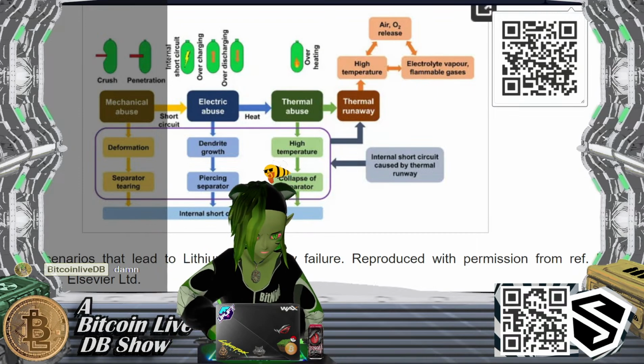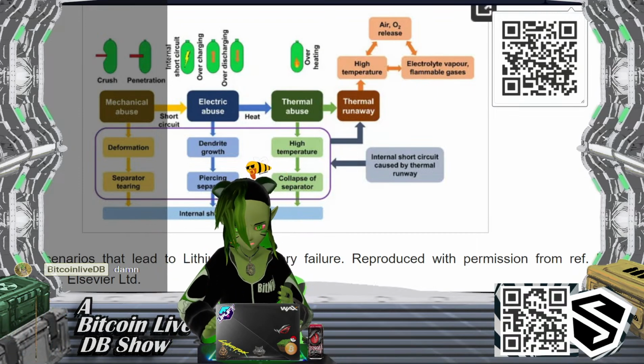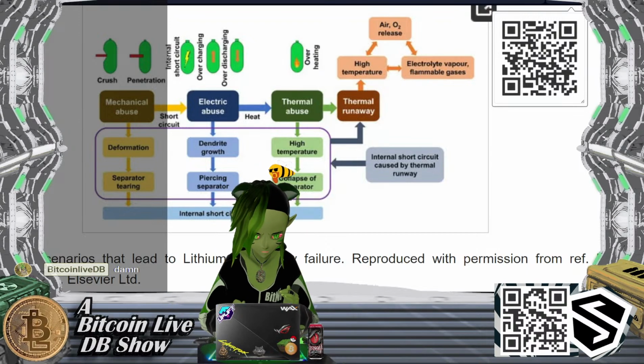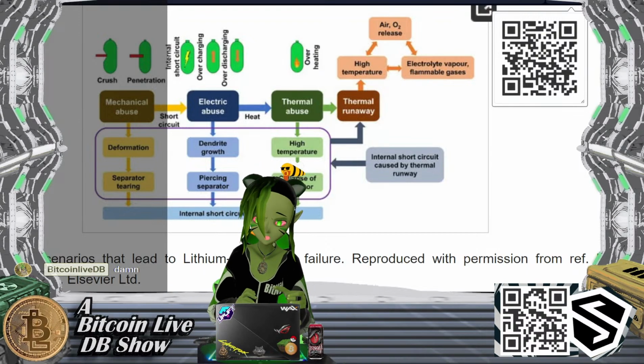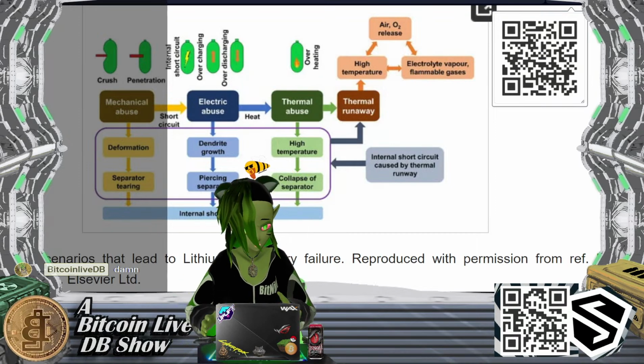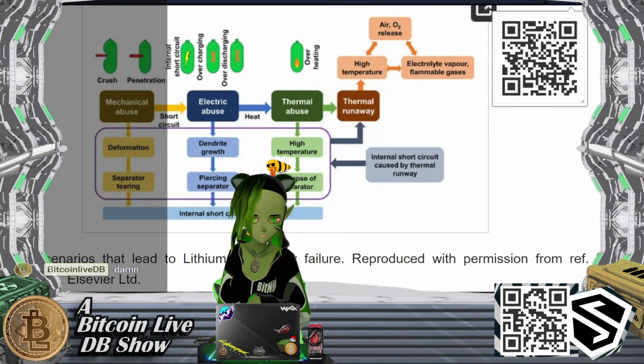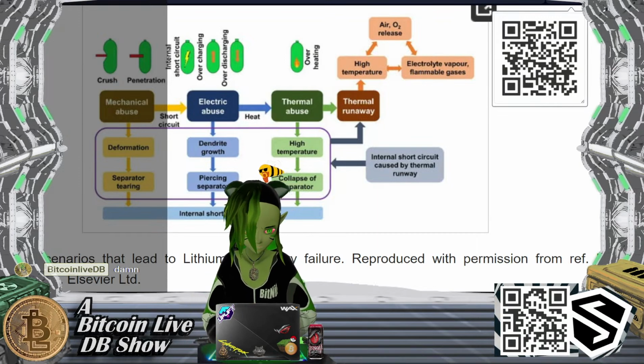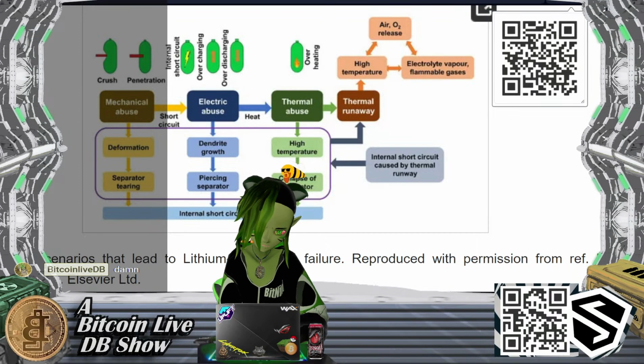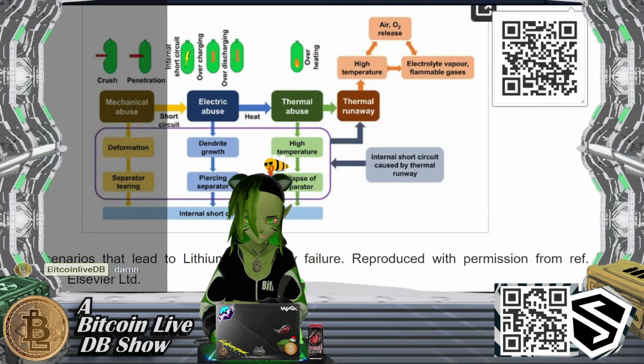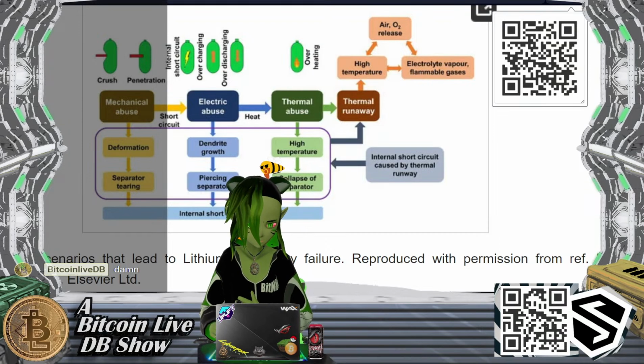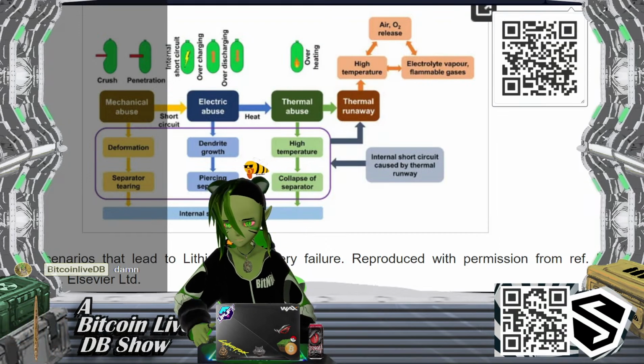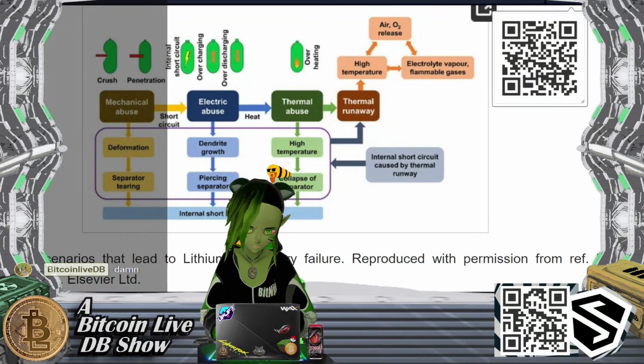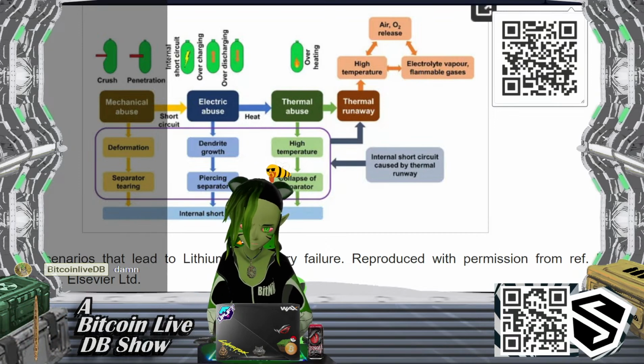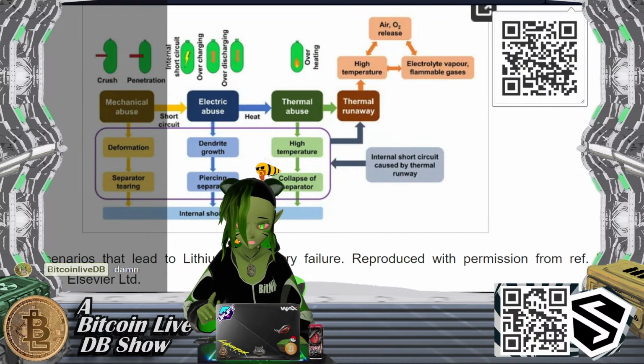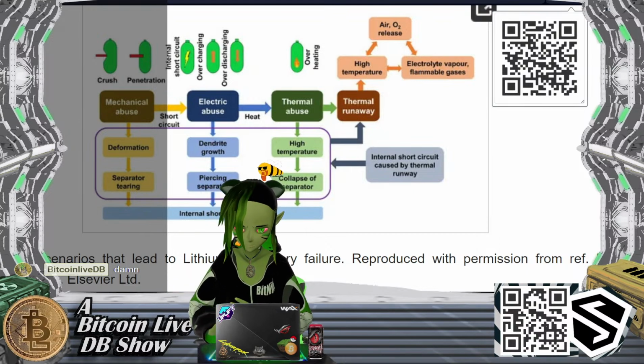So anything done to a battery 99% of the time causes an internal short circuit, which, as you can see, immediately turns into a thermal runaway, almost always, once we have it. Then we get high temperatures, air, O2 release, electrolyte vapor, which is flammable gases, exiting when they can, but until then, it's just a cycle of temperature increasing, O2 having less room as the electrolyte vapors expand. Fast. Very fast.